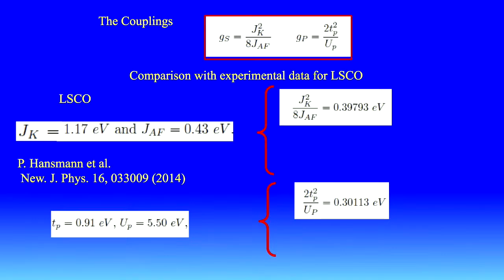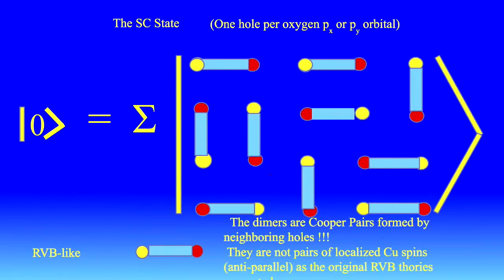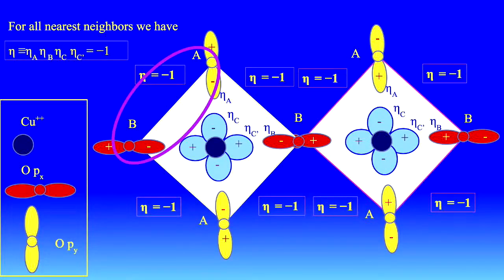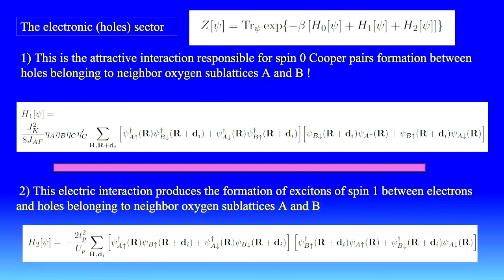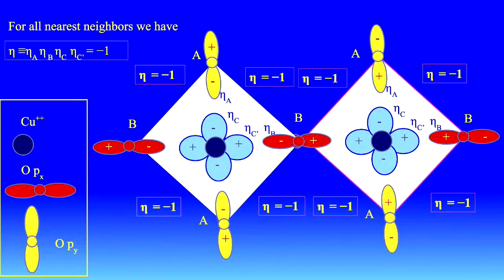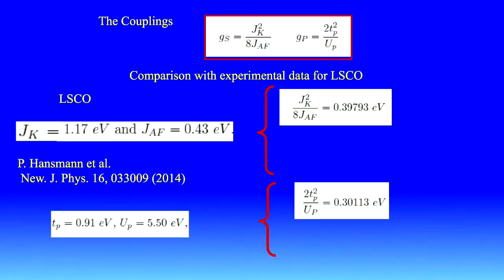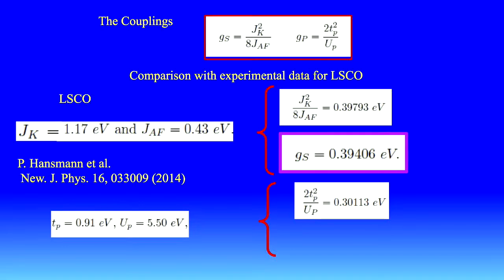Now we start to see that the coupling parameter of the superconducting system is this number here, and the coupling of the pseudogap is this. Now, if you take LSCO, and use the measured values of these two couplings and plug them in here, we get this value. Now, if you look at the measured value, you can determine the measured value of this coupling. You see?